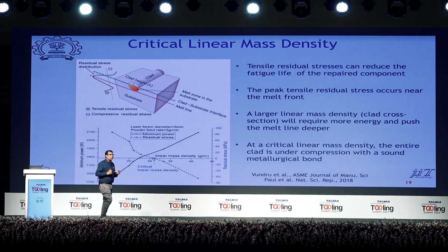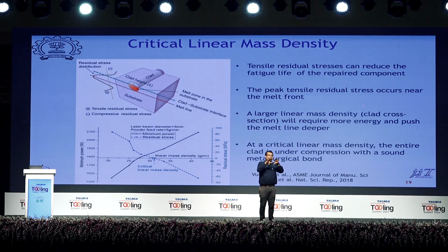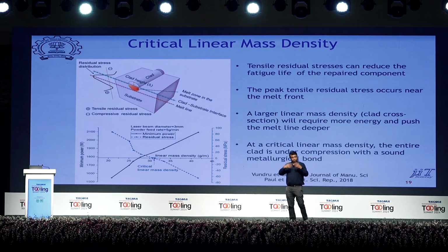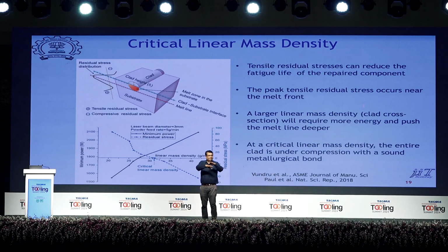Then with all this, our goal was to define something called the critical linear mass density. So what we can do is deposit certain material. It so happens that the maximum tensile stress lies at the melt interface. So you can push the melt interface low, and because of force balance, the top layer will be compressive. If your deposition is compressive, it means you don't have to do a secondary treatment. You don't have to do heat treatment, you don't have to do shot peening to have compressive stresses. So your material as deposited can have very high compressive stresses. So this is what we got from this model. Just by virtue of deposition, you'll have compressive stresses, so no heat treatment, no shot peening required.